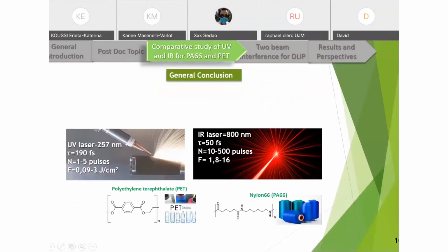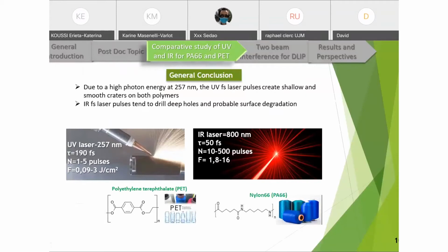So by this project, the general remarks gained from this study are that the UV femtosecond laser pulses can create shallow and smooth craters on these polymers, in contrast to the infrared femtosecond laser pulses that tend to drill deep holes and induce probable surface degradation. However, both are capable of microscale texturing.